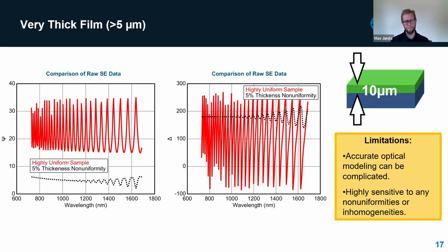And you can see that the measured data is vastly different in the case of just adding a small amount of thickness non-uniformity. And the reason for this is basically because the path length through the material becomes very high when you have a pretty thick film. And so consequently, this means that the light has a lot of distance to be affected by the problems in the film, these non-uniformities, and they really affect the measured spectrum. So the thicker and thicker that films are, as you're trying to use ellipsometry to measure them, any little non-uniformities or issues with the film start to get magnified. And so ultimately, we need good quality films to be able to do really thick cases. Next slide, Lyle.